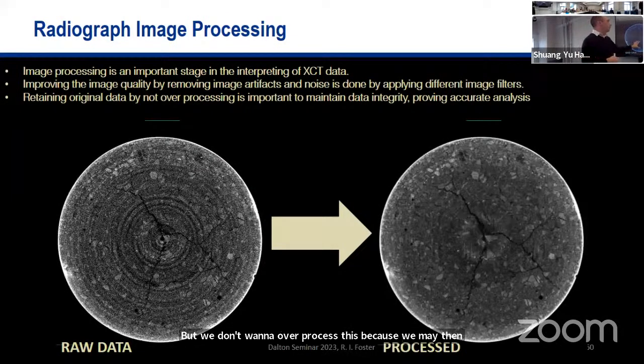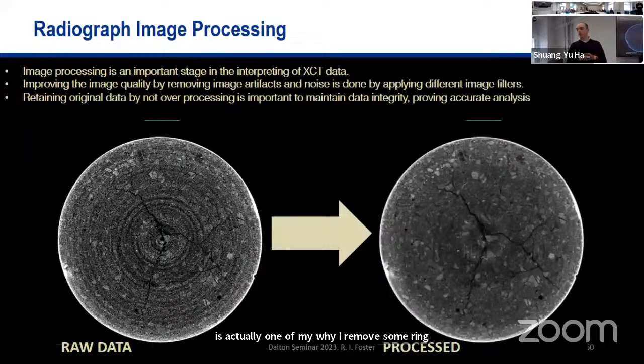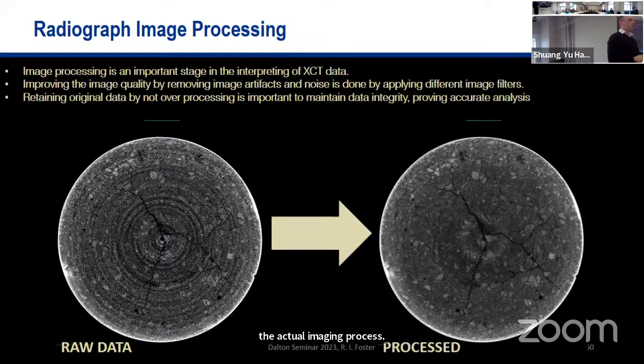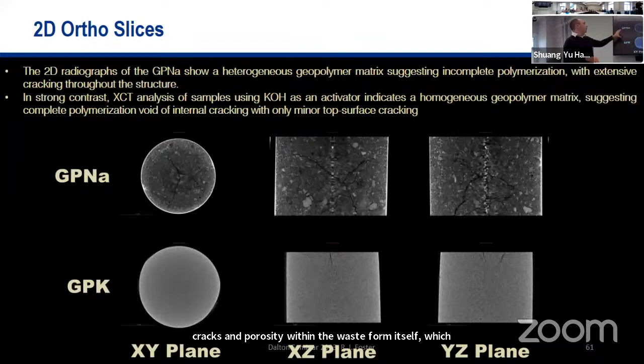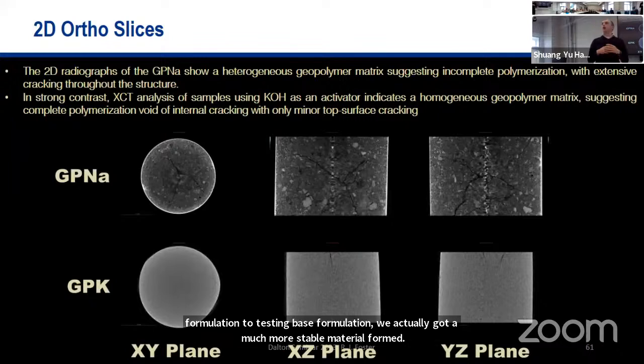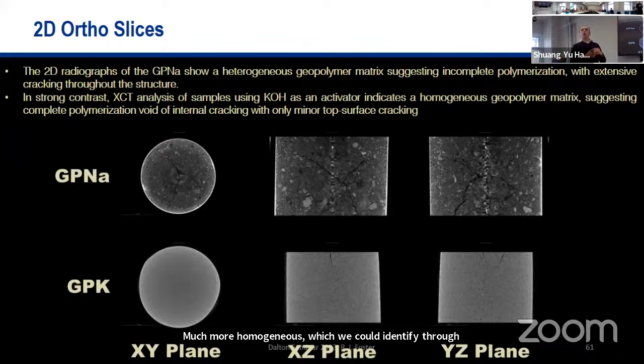This is one of mine where I removed some ring artifacts within the data, which were causing a problem for the imaging process. But we can then see very clearly that we've got cracks and porosity within the waste form itself, which is obviously not a good thing for us to have. When we change the formulation from a sodium-based formulation to a potassium-based formulation, we got a much more stable material formed, much more homogeneous, which we could identify through the use of X-ray CT rather than relying simply on other measures such as compression testing. Both of these actually passed the compression test at 3.44 megapascals, which, when you look inside and see all these cracks and voids, you're dictating that this can't really be used for final disposal.